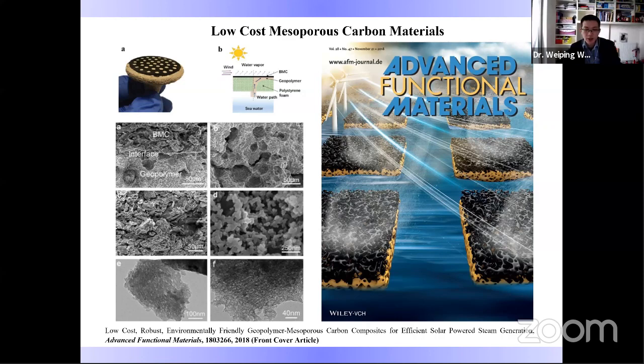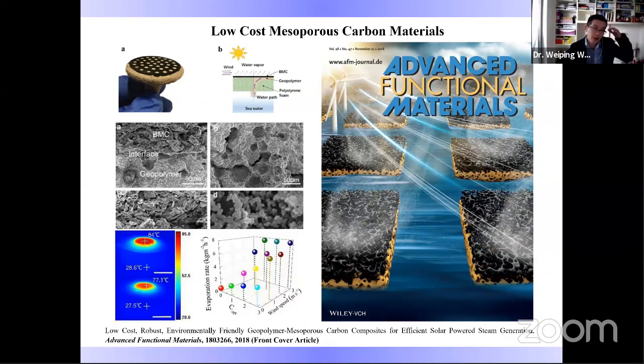Then we have developed this technology in new application areas such as solar steam generation, to convert seawater into drinkable water. Due to the high surface area and the high optical absorption of porous graphene material, we can gain a very high temperature at the surface of the water, and the evaporation rate has reached the world record.